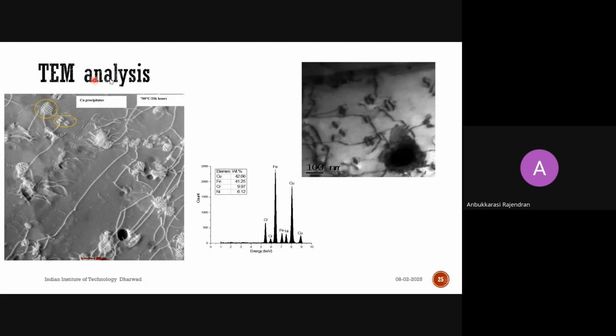Okay, so this is one of the TEM samples we have taken after tensile testing. We can see the dislocation pinning over the precipitate particles, how the dislocation pinning happens, and some regions where you can see the dislocations. Here you can see Orowan looping as well as a cut-through. Okay, so these are the dislocations.